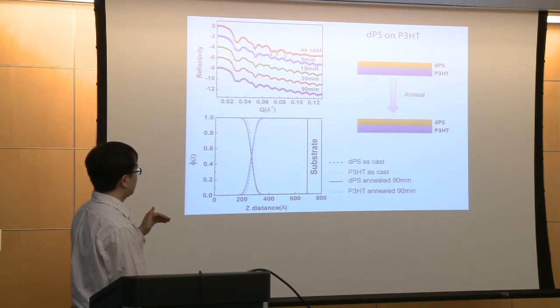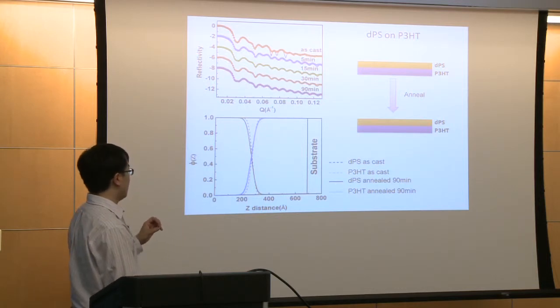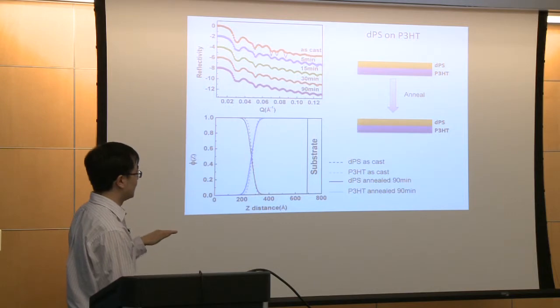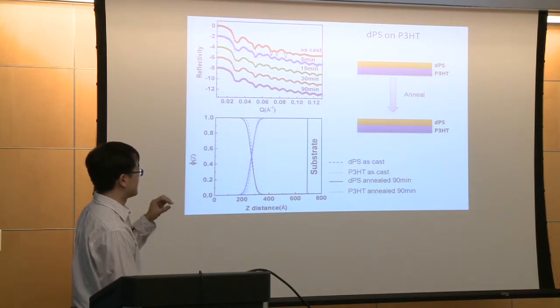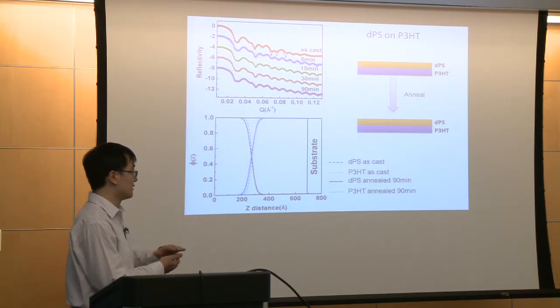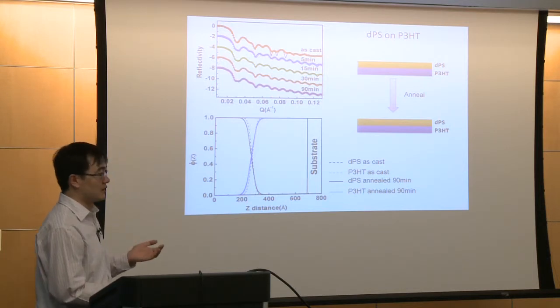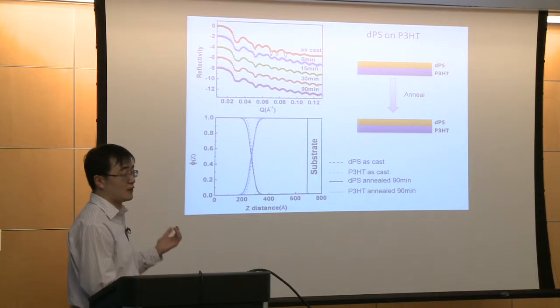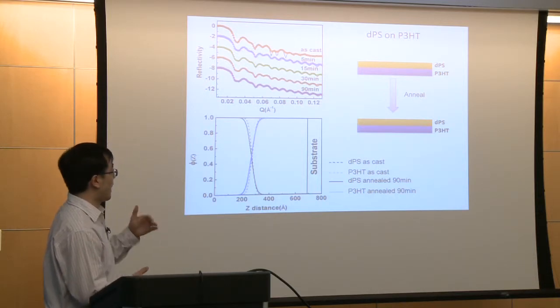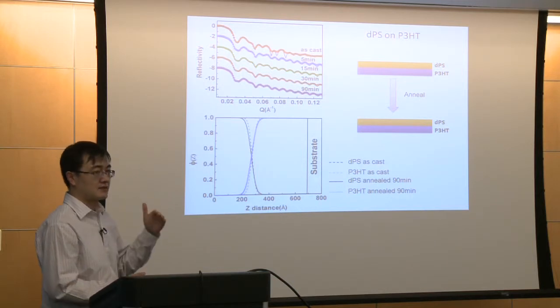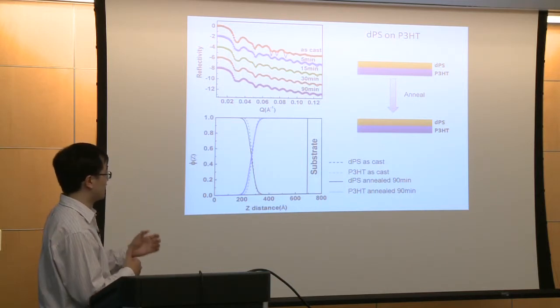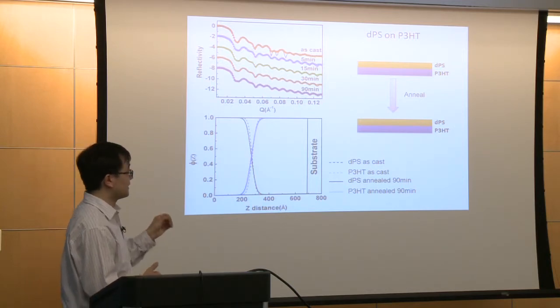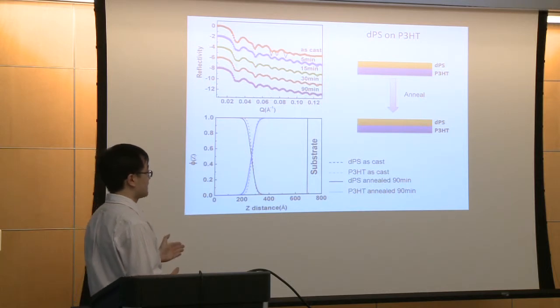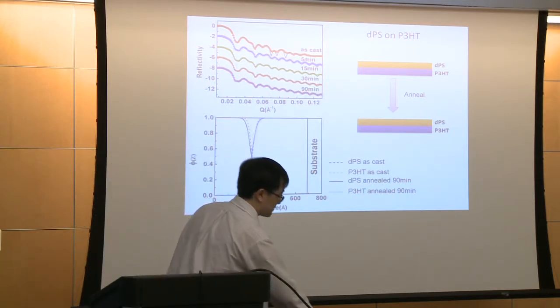So basically, with just deuterated polystyrene and just P3HT, after 90 minutes of annealing, you can hardly see any interdiffusion between these two layers, which means there's very significant repulsive interaction between polystyrene and the P3HT. Otherwise, they would mix together. If you still remember what I talked about from the theoretical simulation, the repulsive interaction between P3HT and the second polymer is a key factor to generate the column structure. So here we prove there is indeed repulsive interaction between polystyrene and the P3HT, which makes it possible for us to generate column structure.